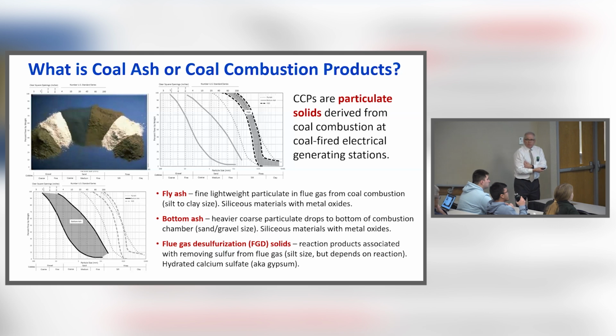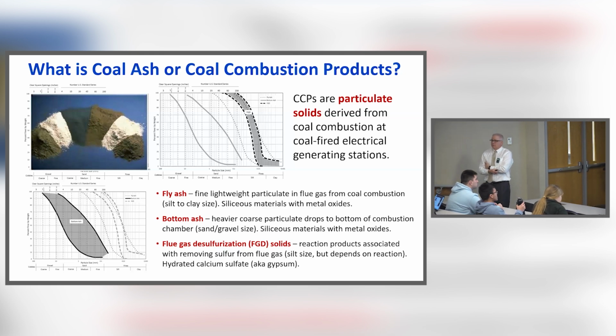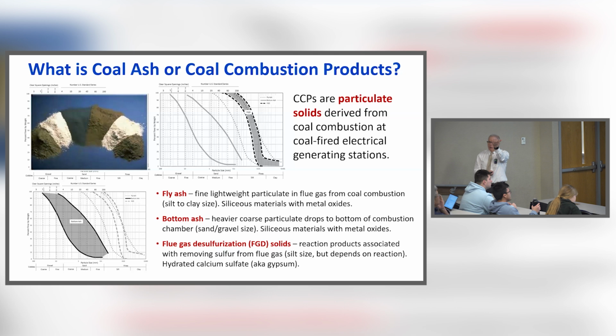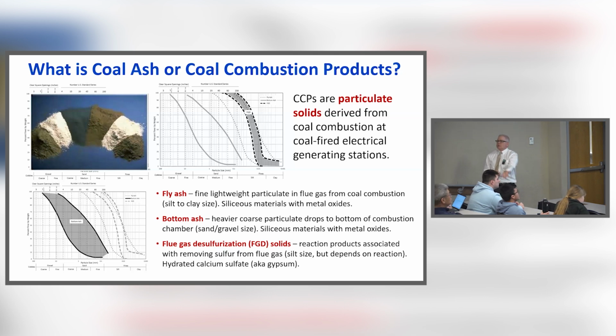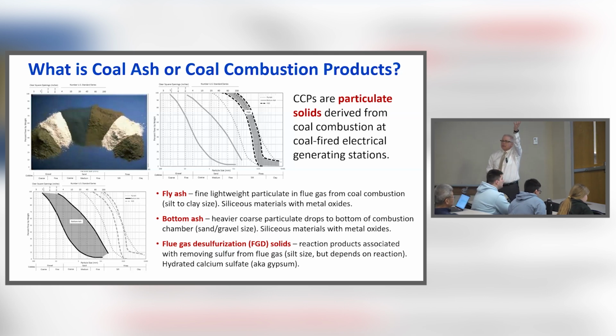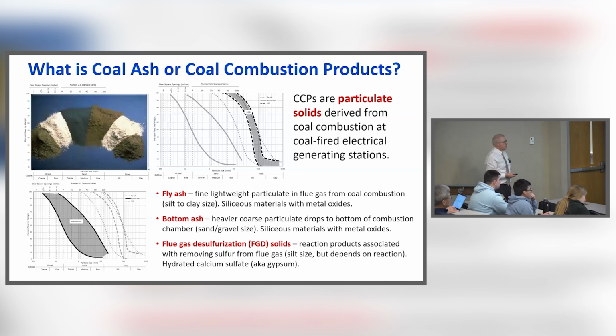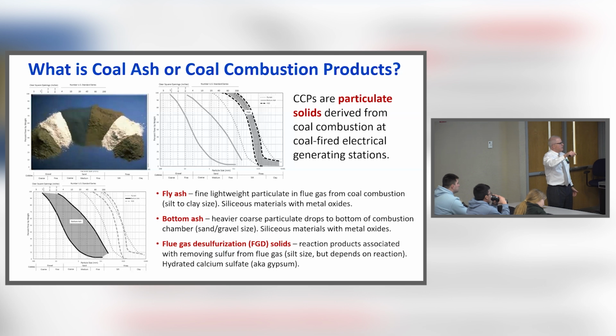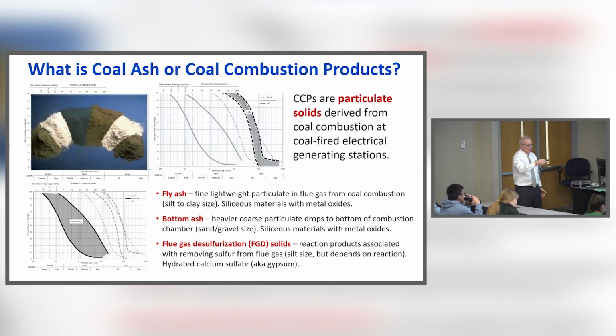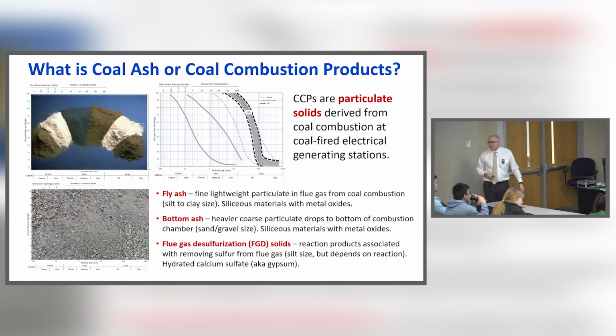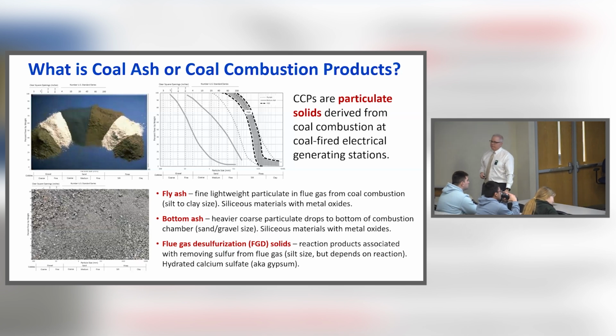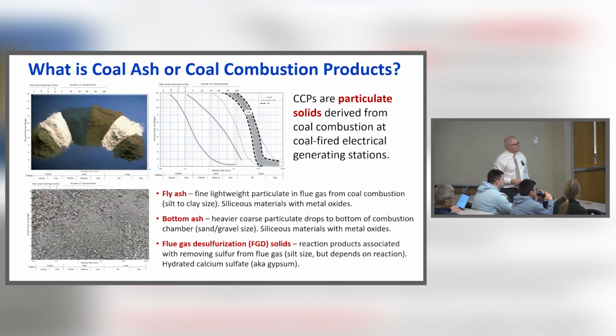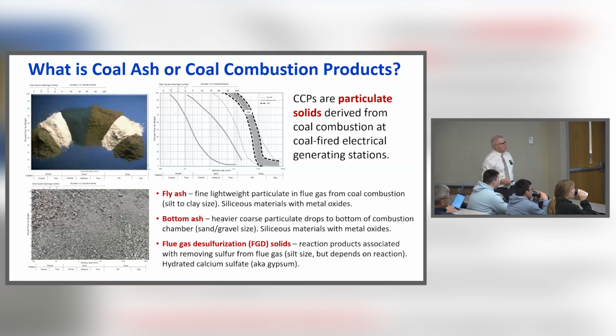The other thing that we generate from that process of burning coal is bottom ash. So we generate larger particulate that are too large to essentially move up in the gas stream and float, and they'll drop to the bottom. That's so-called bottom ash. That tends to be more on the fine gravel to sand size, maybe down in the silt too, but falls into this size of a particle size curve. But you look at bottom ash, it looks like gray sand, all right? Looks like gray sand. And we'll collect that as well.